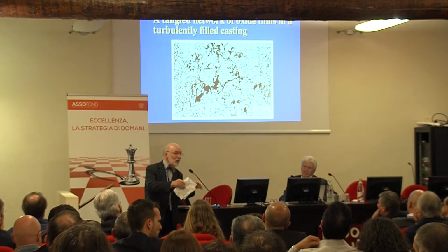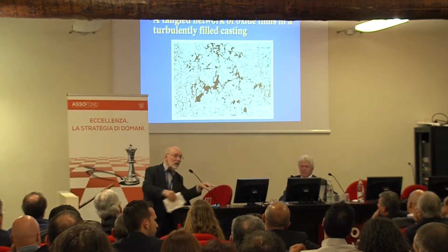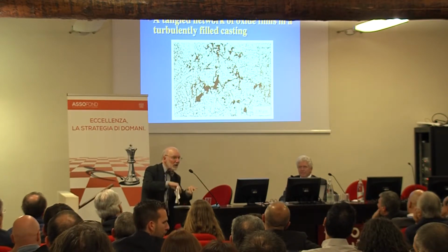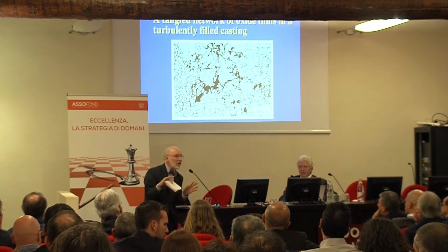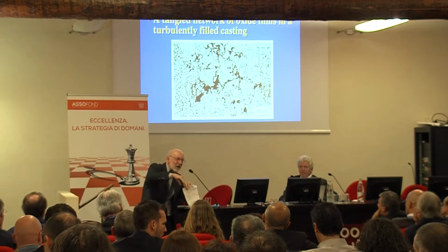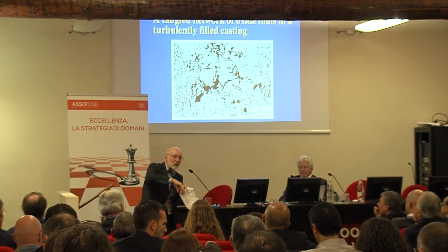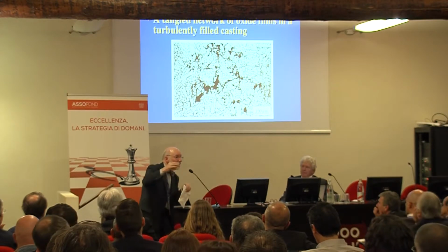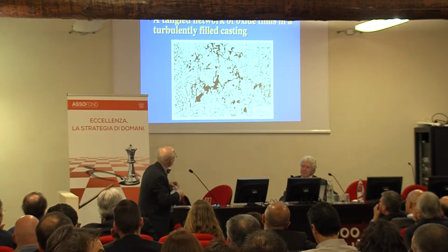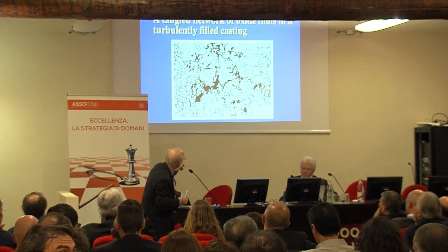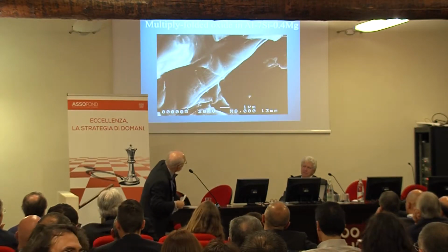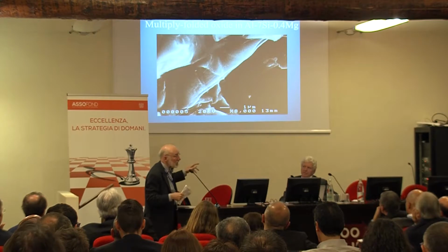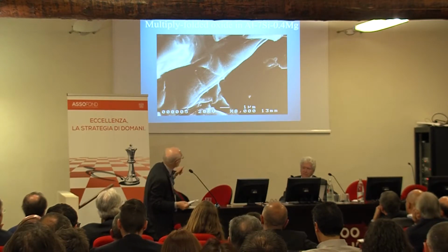The oxide is formed so quickly when the metal folds in. It just folds in quickly, and then it's submerged, and it can't oxidize anymore. So there's so little time for the oxide to grow, it only grows a few molecules thick. And so these films are unusual. We have a look at some other films under the microscope. They're only a few atoms thick.